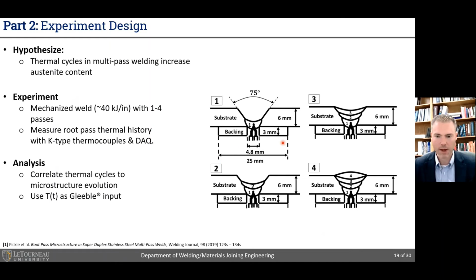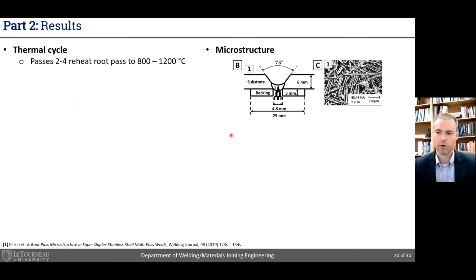We performed a root pass and then embedded a thermocouple up through the backside. We then proceeded to weld that, measure the in situ temperature response in the root pass, section the weld, examine the microstructure, followed by a third pass where we did the same, and then finally a fourth pass. This allowed us to begin to directly correlate time temperature profile, peak temperatures, and the actual austenite volume fraction in the root pass. Here's what we found. Here is our starting root pass microstructure. Using image analysis, binary thresholding, and segmentation, we find nominally 43.5% austenite, as you can see here.